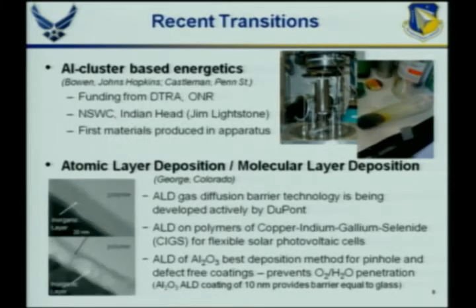So you can make these flexible and very thin. Here's an example. You can see this is the ALD coating, which is very uniform. A CVD type of coating has lots of pinholes and gaps in it, so ALD is very nice as a protective barrier. Boeing is also looking at this type of technology to coat aircraft canopies for protection. We also had an STTR, actually two STTRs, in this area to develop space coatings, where again you can use a very thin coating in the space environment to protect against oxidation from oxygen atoms. And that's been quite successful. For the solar photovoltaics...